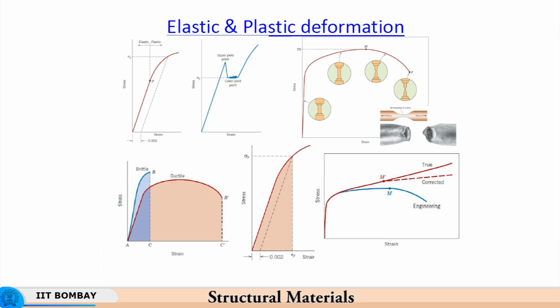Why does it become harder? Because of the dislocation activity in the material, dislocations multiply, and these dislocations result in increased work hardening of the material. So, the increase in strength of the material results in a stable deformation, because although the cross section depletes, the strength has increased, and therefore, it is able to balance the external load that has been applied.